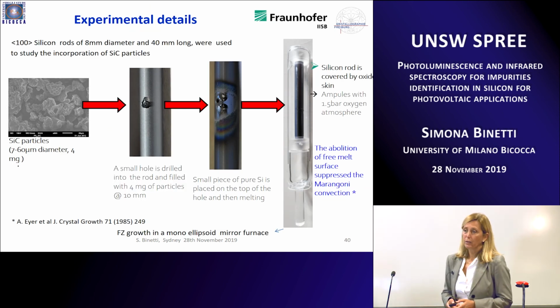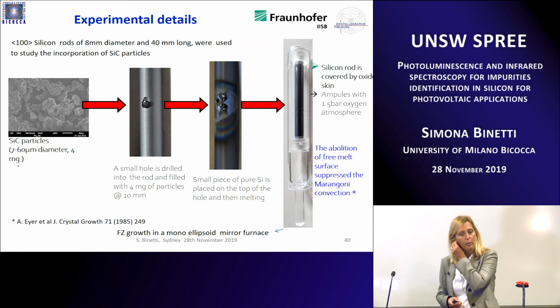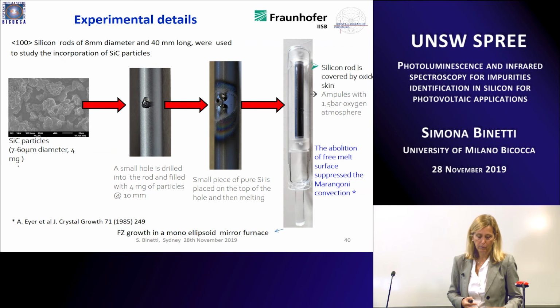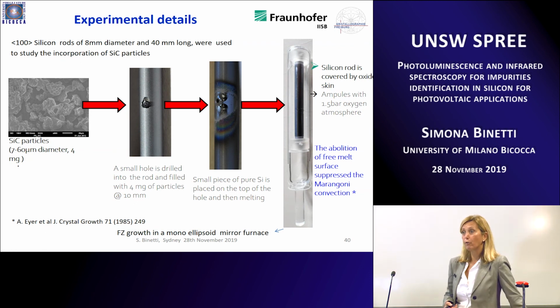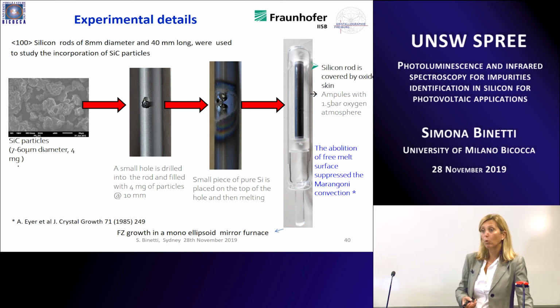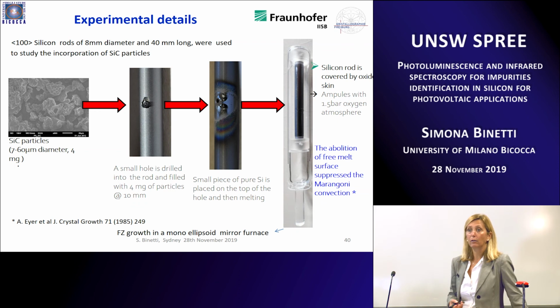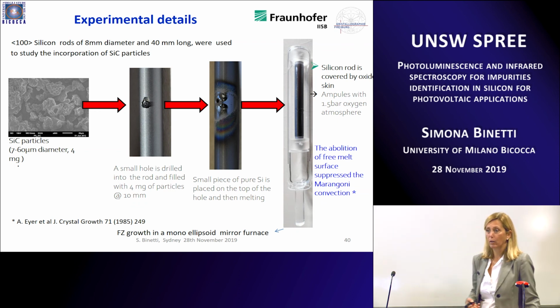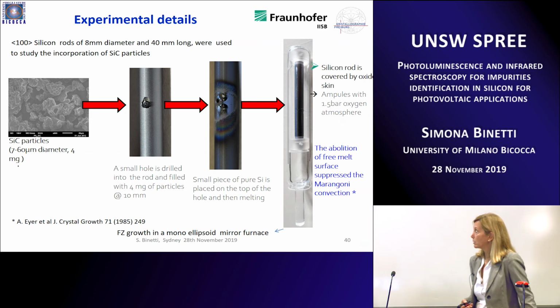Silicon carbide was studied by the German group because, in the case of multicrystalline silicon, as you probably know, the formation of silicon carbide particles is very deleterious for PV applications. They are formed during the solidification process, and so are incorporated and can move along the ingot and can create a shunt to the solar cell if you make a solar cell on a wafer in which you have silicon carbide particles.